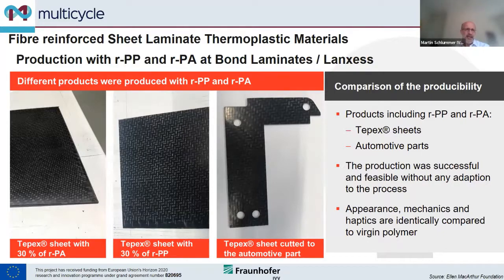Another very nice demonstrator was to go back with the polypropylene and polyamide into laminated sheets. This is a glass fiber reinforced sheet made for the automotive industry. This was done by the partners Bond Laminates and Lanxess. Here we could make use of 30% of RPA and 30% of RPP. We could have gone higher, but then it was a bit more tricky to adjust the parameters, so it was not that it was not possible at all. It was just that 30% was possible without any change in the process. They just took the material as it is, as they would virgin, put it in, and it worked directly.